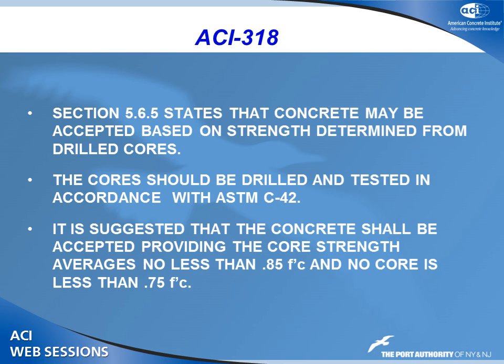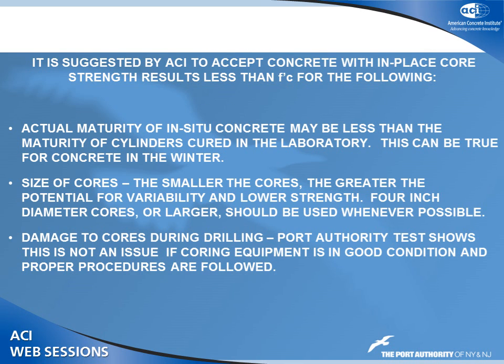Okay, why do we have, in general, lower core data? Or at least that's the perception. Well, for one, I guess the idea is maybe the maturity of the concrete in place is different, and that's true, especially during the winter months. But for the most part, maturity is not an issue. The maturity of the concrete in place usually far exceeds the 28, 56-day breaks by the time we get around to coring. We usually have 1 or 2 meetings where we exchange blows, and then we go and we core. So it's not 56 days. It's usually 120 days. So I don't think maturity is an issue.